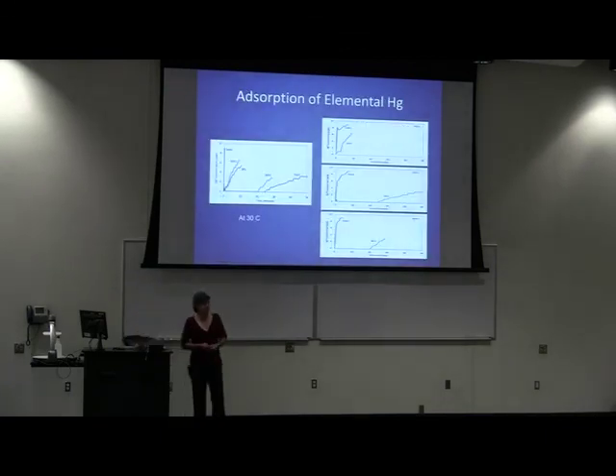So the question is, does it work for mercury vapors? This is at 30 degrees C, and then this is a comparison at 140 versus 30. What you see here is mercury concentration versus time. What this shows is immediate breakthrough. So it didn't absorb anything at 140 degrees, but at 30 degrees, it has some capacity for mercury, which isn't bad.